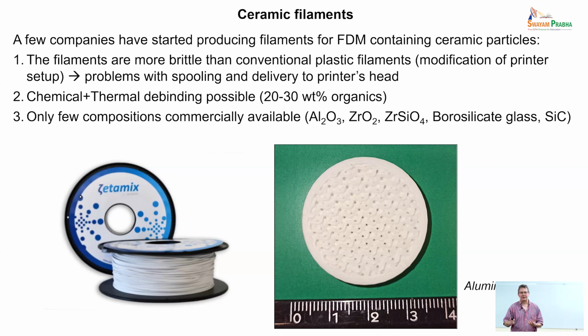You cannot increase the amount of ceramic particles, otherwise the filament becomes too brittle and it simply cannot be printed. So you have this two polymer base binder. You chemically remove one of the two components, and it's about 20% of the entire polymer. And this creates some porosity, which is extremely useful because then the rest of the polymer is decomposed thermally. And you have a lot of gas that has to be released. And if there was no porosity inside the solid part of the material, the part will break.